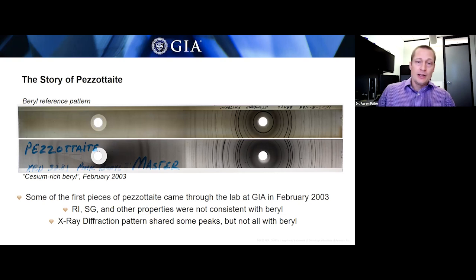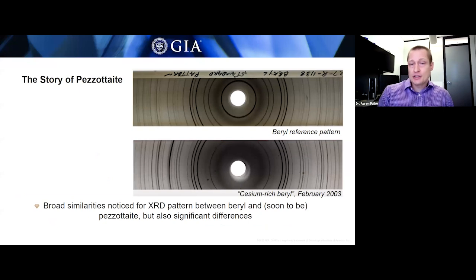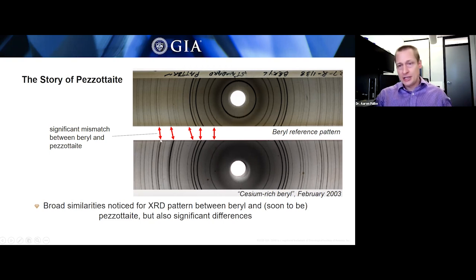And because people had already realized this is probably a beryl group mineral, they compared this pattern to the beryl reference pattern. And what they saw was that there were some obvious similarities between beryl and this new cesium-rich beryl. Some of those lines line up pretty well with each other, but they also noticed some pretty significant differences. They started to realize that some of these lines have a higher intensity in this new mineral than they do in beryl. And in some cases, those lines are not only different in intensity, but they are also shifted in position on the diffraction pattern. So they started to realize that this was probably a new mineral.